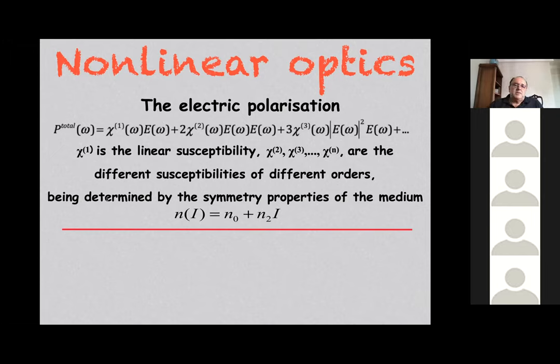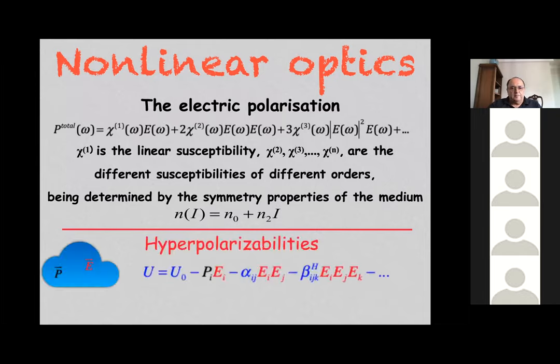And what happens is that the index of refraction of this medium, for high incident electric fields, is dependent on the intensity of the beam. So here is the index of refraction dependent on the intensity: the usual linear index of refraction, and this contribution here is the nonlinear part. So we are able to measure this N2 for the different ferrofluids, and this is related to the real part of the electric susceptibility.